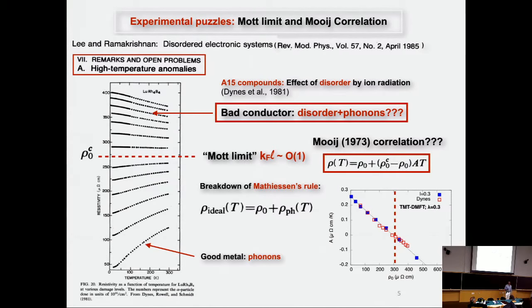Maybe it's just some weird and complicated behavior. By the way, for those who are interested in phosphorus doped silicon, Gabe Bepley gave us a beautiful talk saying that soon maybe we'll be able to go back to this problem. When you look at phosphorus doped silicon, you see something similar to this. And this happens about 10% in density from the transition. So people have tried to use scaling theory to understand it, but you cannot scale the data when the slope changes sign. This is impossible. So this is part of the mystery.